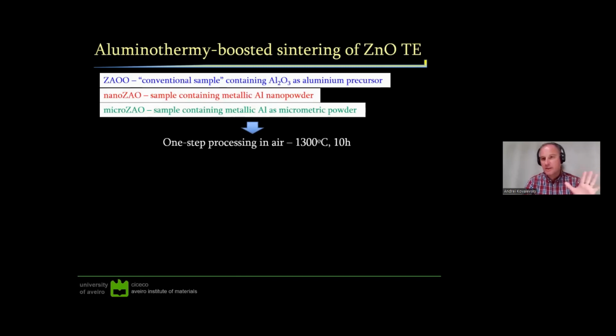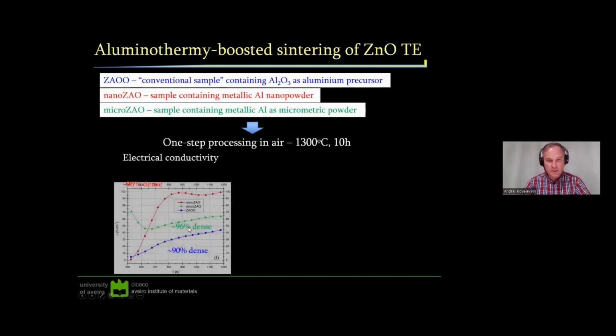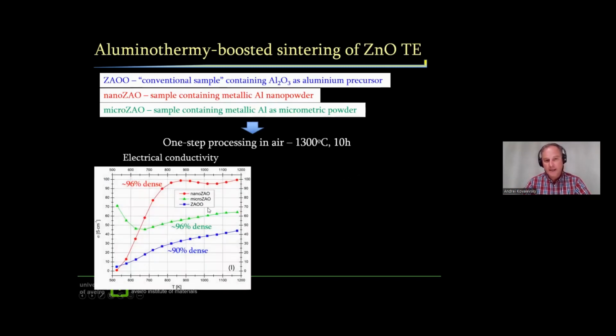We applied the same processing conditions for all samples, obviously, to have a good reference point, and found out that in the case of electrical conductivity there was a significant increase. This blue line corresponds to the conventional sample.